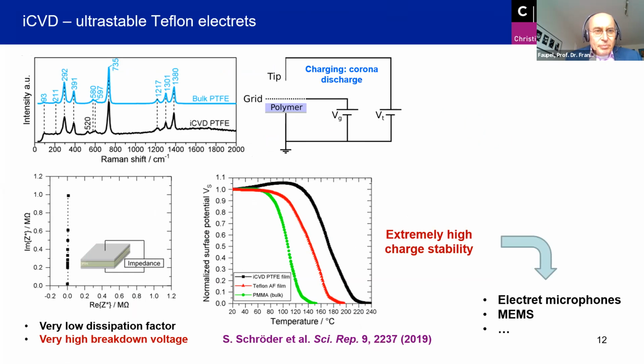Let me show you one typical example. We use the initiated chemical vapor deposition technique to produce thin film electrets. Electrets are similar to permanent magnets. Here you have permanent charges in a material. For developing electrets, you need materials with a very high breakdown strength. And here's a typical example of a Teflon film. This is bulk Teflon, and this is iCVD deposited Teflon. Different from other techniques to deposit organic thin films, iCVD allows you to completely preserve the chemical structure. So here in this Raman spectrum, you see all the peaks of the bulk material also in the thin film. And compared to bulk materials, these iCVD deposited materials have an extremely low defect density. The breakdown strength is about a factor of 10 larger than for bulk materials.